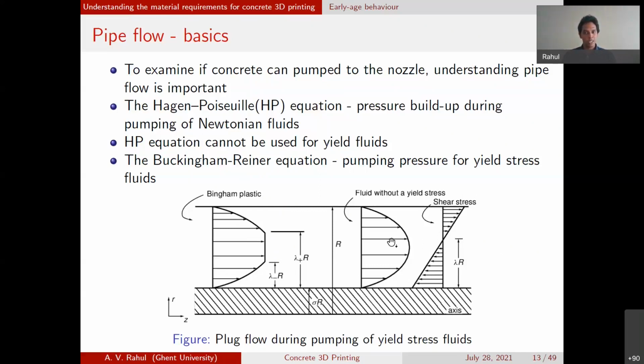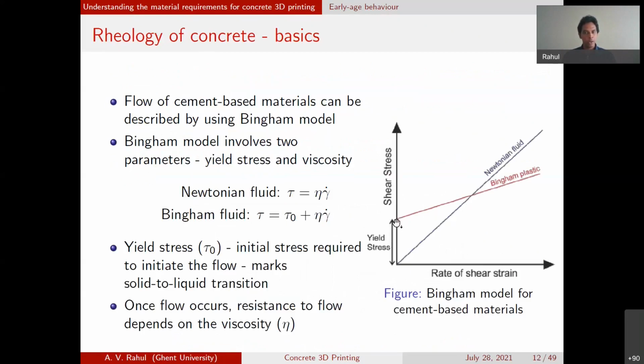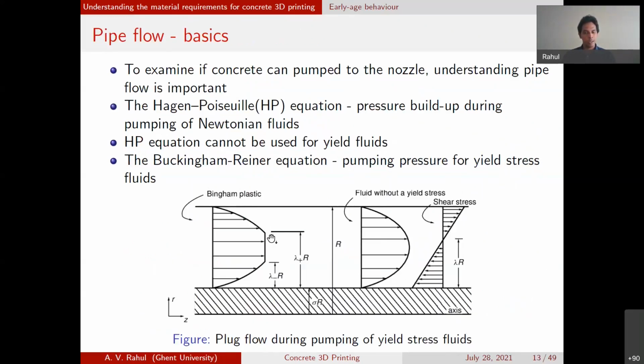Now, if the shear stress drops below the yield stress, below a particular stress level, it doesn't flow, it behaves like a solid. So let's say that the stress level at this point reaches the yield stress, then below this point here, it behaves like a solid. So you see more of a rigid body translation of the material below the point where the shear stress decreases to less than its yield stress. And towards the outer edges of the pipe, you see shearing occurring. As a result of that, you see a parabolic profile more closer to what you associate with a Newtonian fluid.